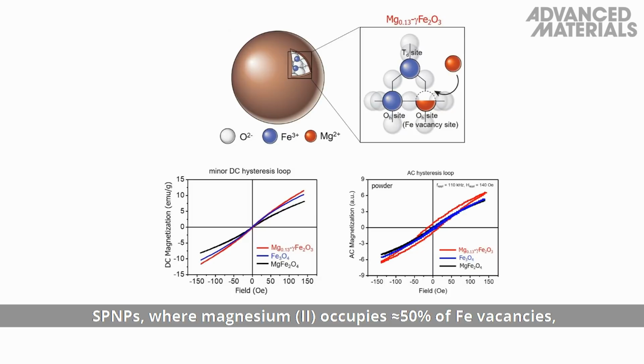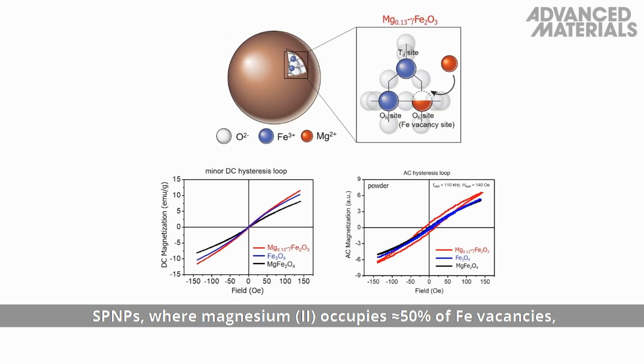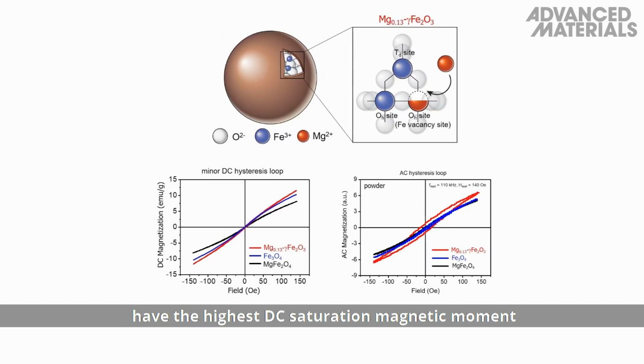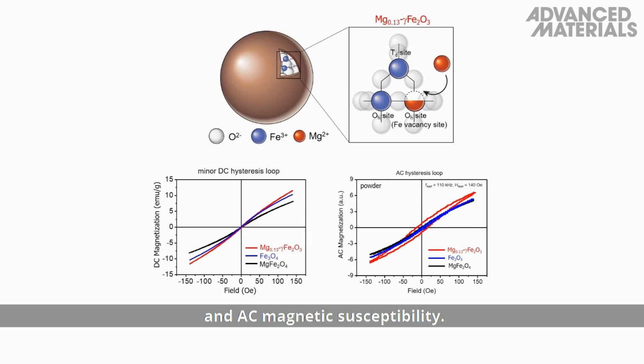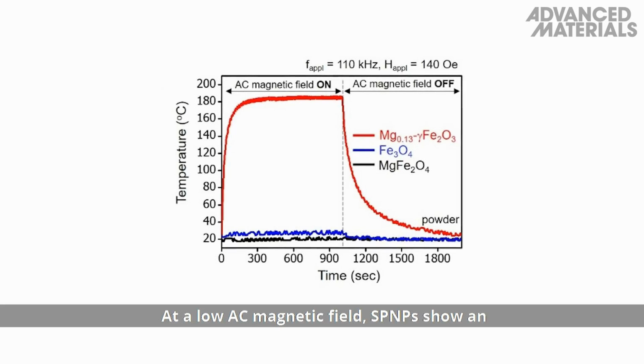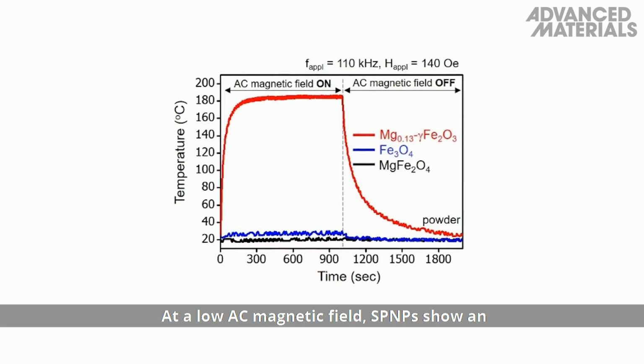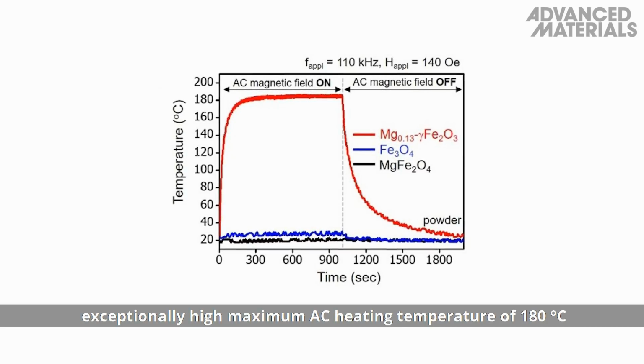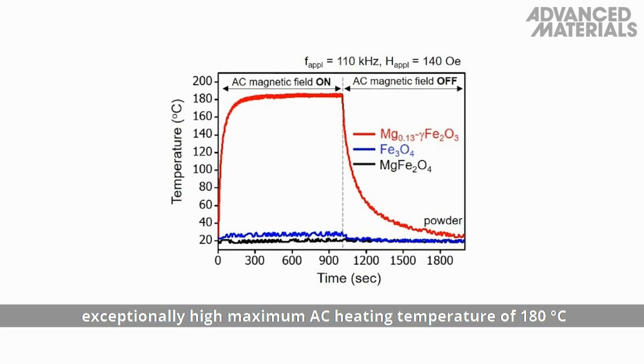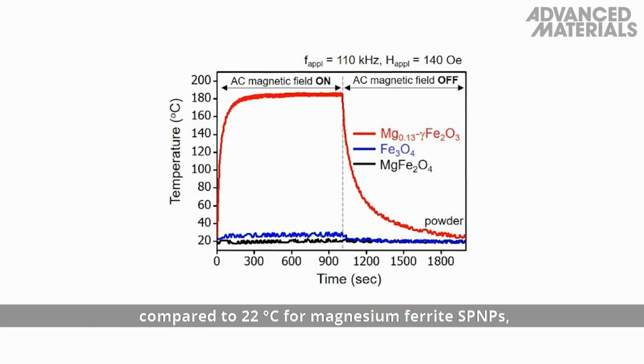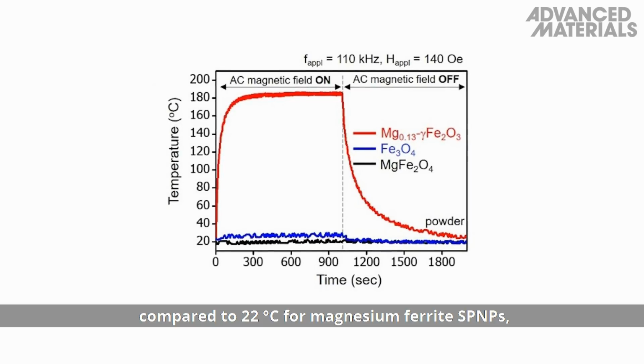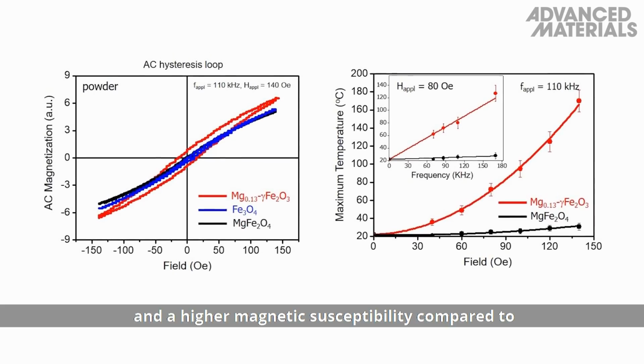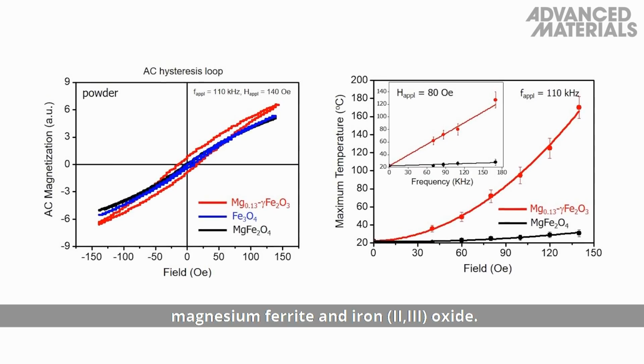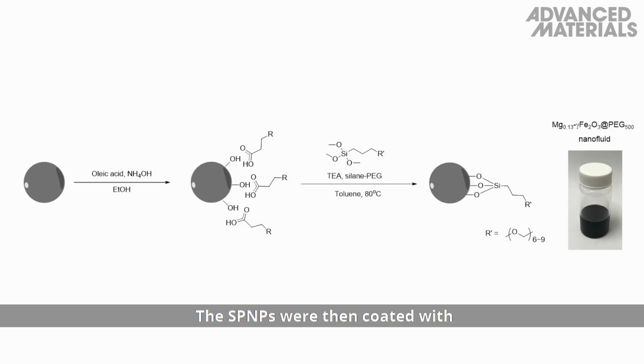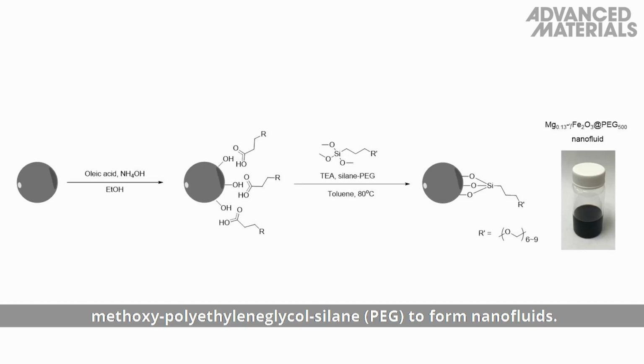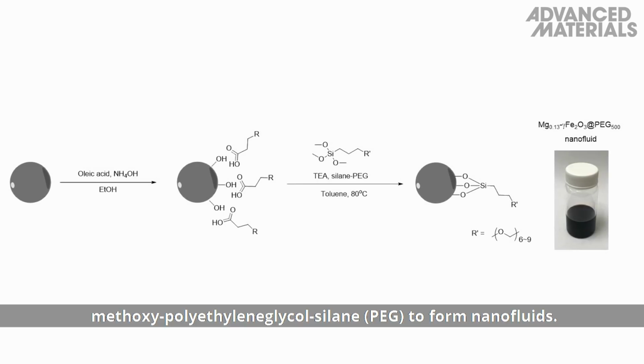SPNPs, where magnesium(II) occupies approximately 50% of iron vacancies, have the highest DC saturation magnetic moment and AC magnetic susceptibility. At a low AC magnetic field, SPNPs show an exceptionally high maximum AC heating temperature of 180 degrees Celsius, compared to 22 degrees Celsius for magnesium ferrite SPNPs, and a higher magnetic susceptibility compared to magnesium ferrite and iron(II,III) oxide. The SPNPs were then coated with methoxy polyethylene glycol silane, or PEG, to form nanofluids.